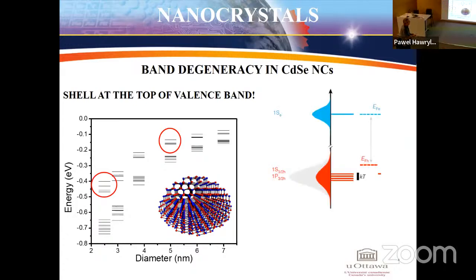Okay, and if you now look at the population of this shell, so electrons and holes in this shell, then you will find that the chemical potential, the Fermi level of electrons, is tied to this 1s level in the conduction band, but it is pulled into the band gap for the band of states for a given temperature. And what you need for gain is that this difference be bigger than the gap. Okay. So how do we go about making this happen?